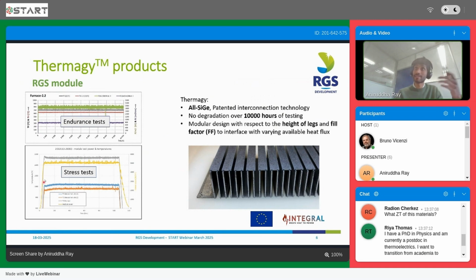We also did stress tests where we expose the module, especially the hot side, to above 1,000 degrees centigrade, and we look at what happens at the bonds. And indeed, the bonds are quite stable. That is key for applications where you might have some kind of thermal shocks, for example waste heat recovery. We also patented the way of bonding these materials such that it's quite tunable.